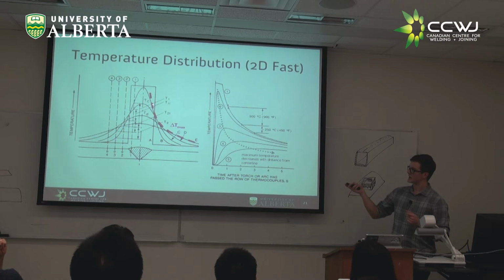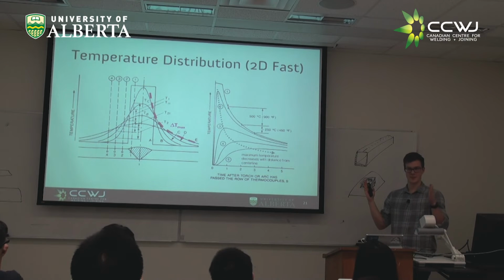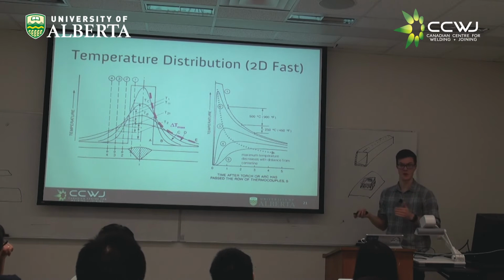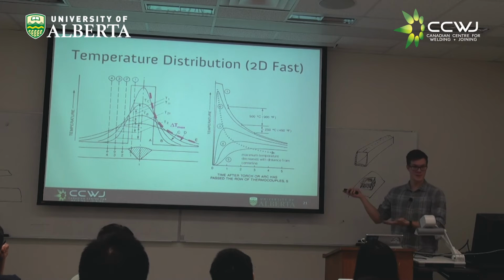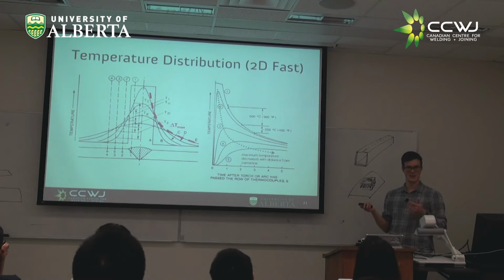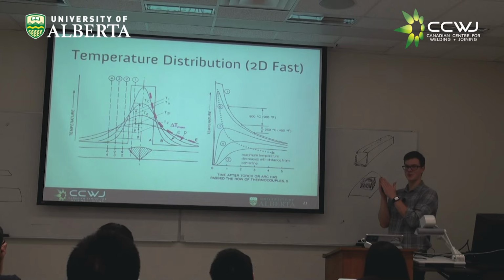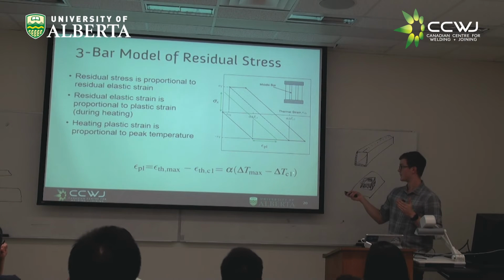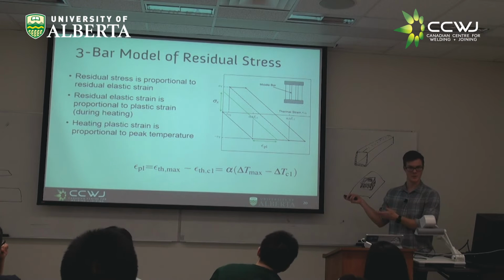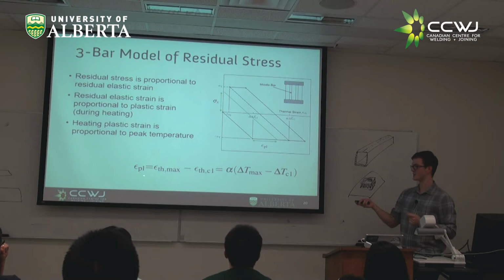If you trace down the side of those curves, you end up with this shape, which is actually an inverse shape, where this max temperature is proportional to 1 over the width. And that is the maximum temperature at each point in your weld. This is what we needed, right? So we need to know what the maximum temperature each point gets. We subtract that from this critical temperature, which we can calculate based on material properties. And from that, we get plastic strain.